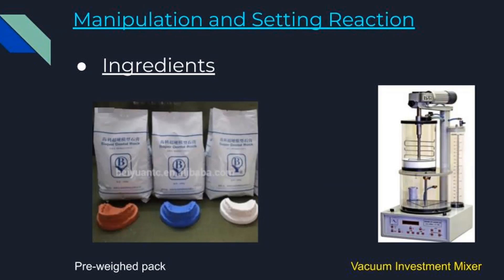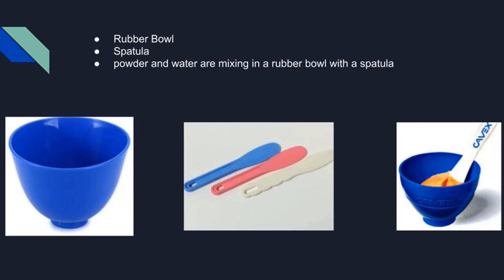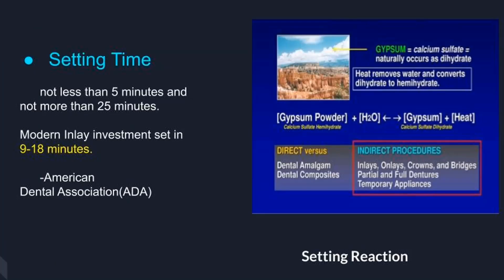Investment materials are supplied in bulk or pre-weighed packs. In manipulation, the measured quantity of powder and water is mixed manually using a flexible bowl and spatula, or a vacuum mixer. A blue rubber bowl and a plastic spatula are shown on the screen. During manipulation, the setting reaction occurs — hemihydrate becomes dihydrate in the presence of water. According to the ADA, setting time is not less than five minutes and not more than 25 minutes. Modern inlay investment sets in 9 to 18 minutes.